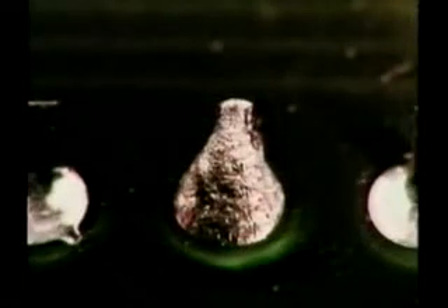This is a cold solder joint. The solder was melted by the iron rather than by the parts to be soldered, and the flux may have burned away. The connection never became hot enough to allow wetting with the solder. Here's another cold solder joint. Notice that the surface of the solder is dull and grainy. The solder does not flow out to a thin edge, and the fillet is not properly concave.